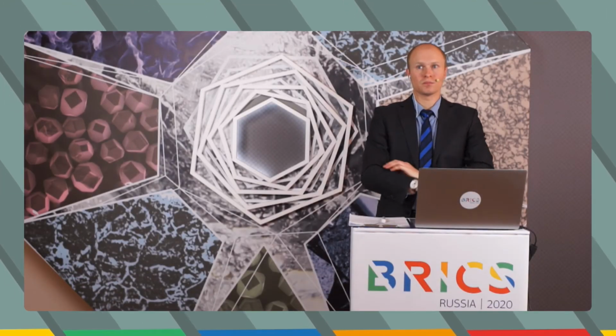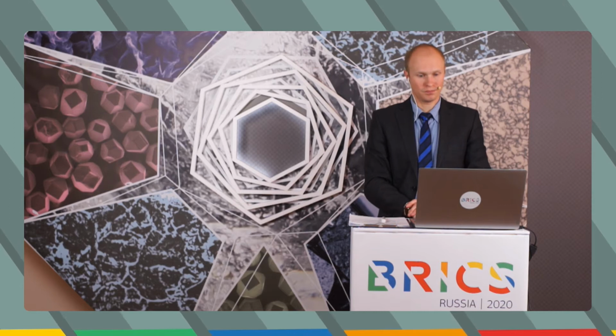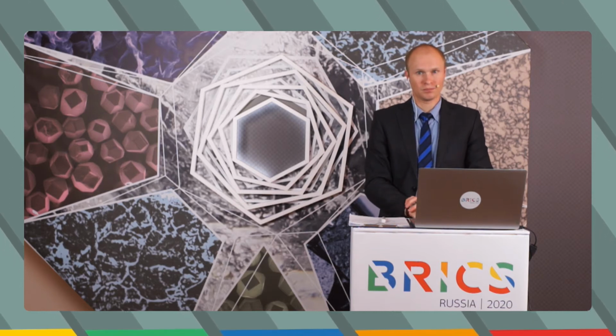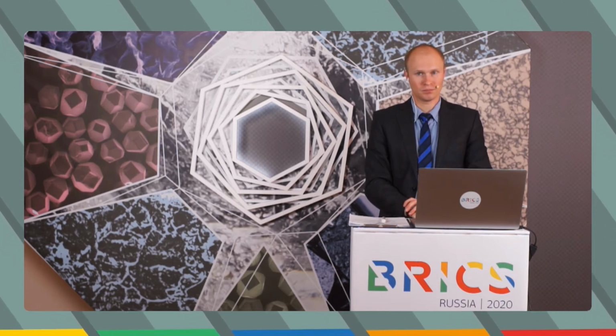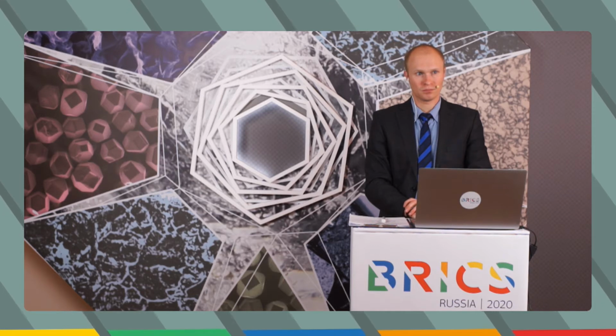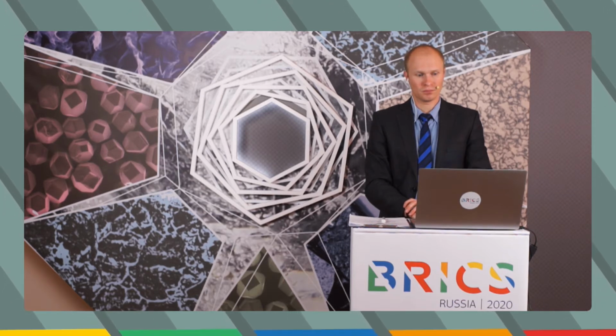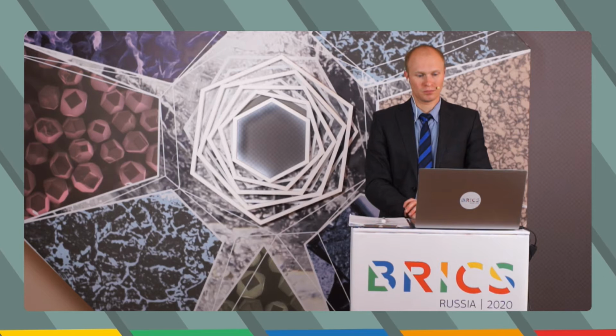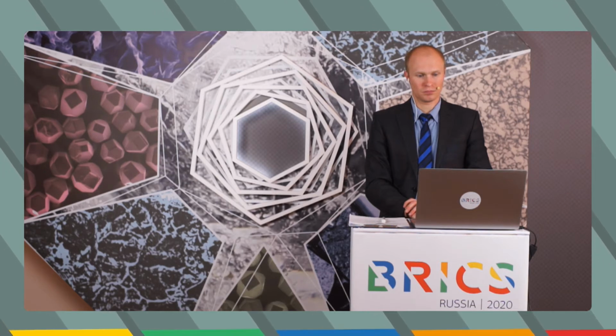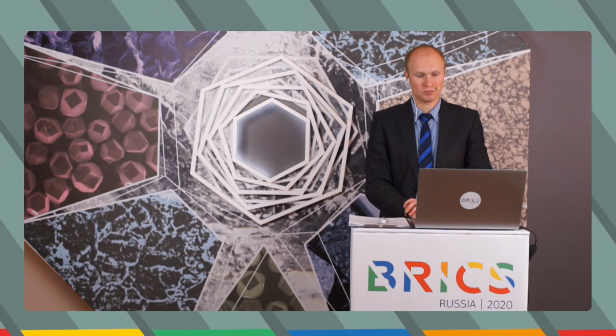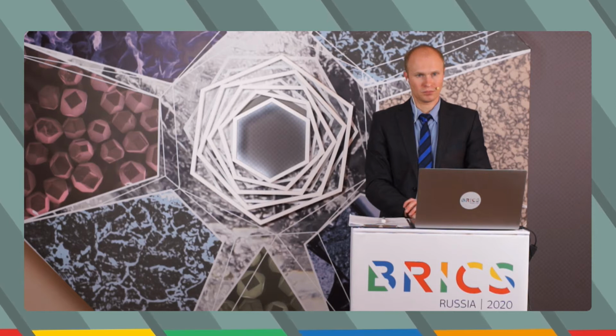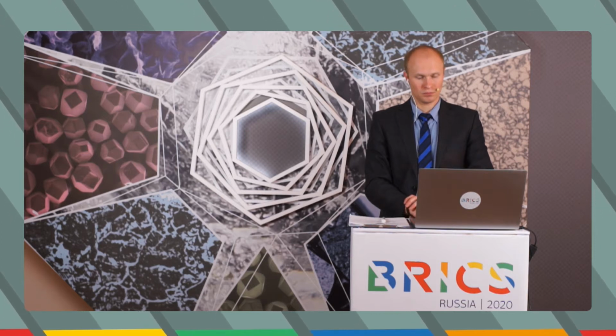If they behave as particles, we could actually associate this behavior to the population of flexural phonons. So to the left of this line here, I have the phonons in a coherent regime, so coherent heat transport, and to the right I have an incoherent transport. We can associate this behavior to the population of the flexural phonons. It's all described in this paper here.